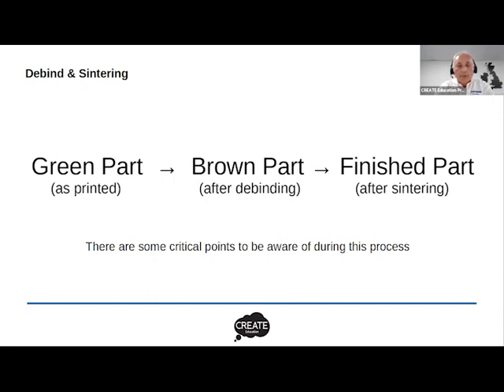But the other good thing about this robustness is it's robust, but at the same time the material's quite soft. And that means that you can do some kind of post-processing of your own before they go through this debind and sintering phase. You could be rubbing the parts down using abrasive paper, perhaps to get rid of any layer lines. Shot blasting of parts works really well. It tends to give a part a really nice satin finish when it comes out of the final sintering process.